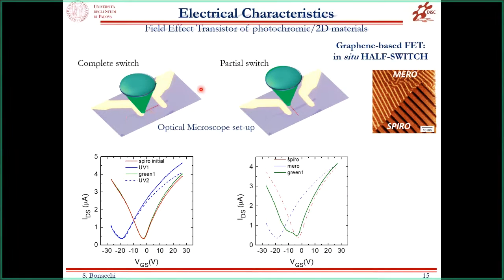Here, this is the device, this is the gold electrode, and if we induce a photoswitch all around the graphene flakes below here, for instance, as you can see my pointer, we can totally induce a switch in the electric properties, so a totally n-doped effect on the graphene flakes. But if we partially switch the